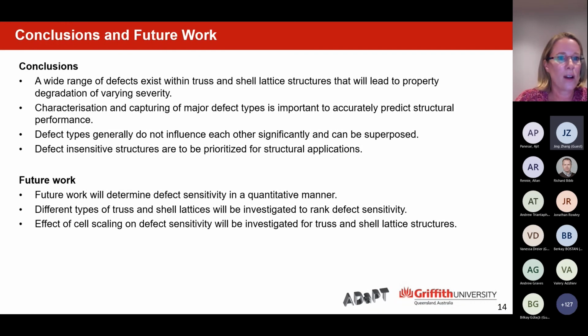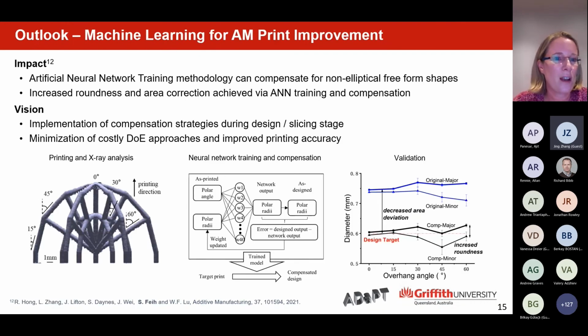Now, as an outlook, I just quickly want to show something here about machine learning. I haven't talked at all about process improvement. We've basically gone with the defects we have, assuming we will always have some defects. We can use machine learning, and we've done that here. Again, Chen has published this in Additive Manufacturing this year. We can use artificial neural network training to compensate for truss lattices being not perfectly round in printing, depending on overhanging angles. So we've shown here that, again, with X-ray data collection, we can come up with the overhanging angle.